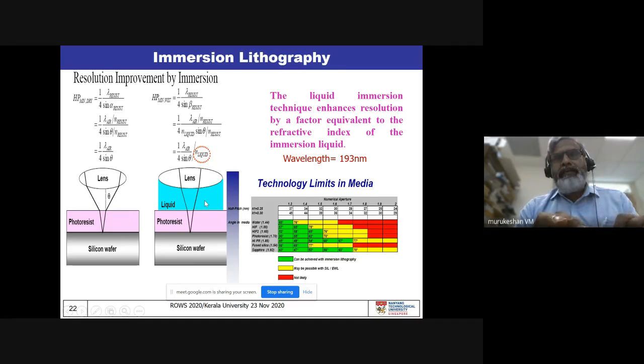But the problem is that industry grade liquids have limited refractive index. The maximum achievable refractive index is about 1.65. So what to do then? Then they started using very high index glasses, such as LuAG, sapphire. Even a small glass slide, the size of the glass slide that you normally use when you go for a blood test, for example, costs a hell of a lot of money. That's about a few thousand US dollars. So it's very expensive. But even then, you cannot get more than a refractive index of 2. You see that? So the achievable reduction in the dimension is still limited by this.